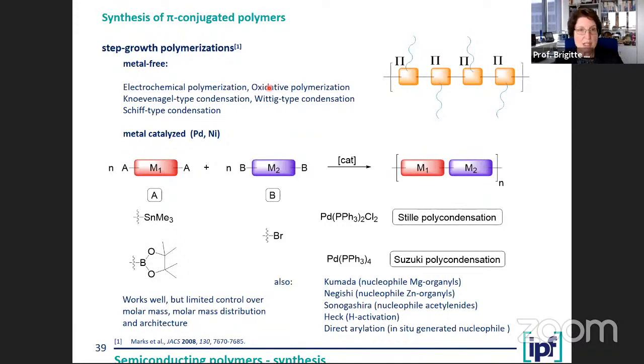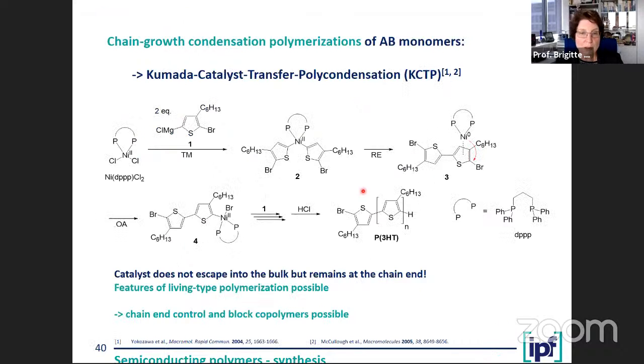The synthesis usually done for such pi-conjugated polymers are step growth polymerizations, where you have an AA component and a BB component, which are coupled together by C–C coupling. Much of it is Stille condensation or Suzuki polycondensation. You know, also nice name reactions like Kumada, Negishi, Sonogashira, Heck, and so forth. Also, materials are beautifully developed and work well. You need a catalyst, that's important, and it's a step growth material. And you might all remember there's chain growth and step growth, and in step growth there are often limitations. You need a very high conversion and very efficient reactions to finally come to a polymer.